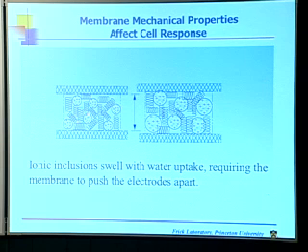Well, as the cell starts to run, it makes water. Some of that water ends up in the Nafion. Okay. Where does it have to end up? It has to end up in these pools. So these pools have to expand. Well, the only way the pools can expand is if the material expands or swells. It's pushing against those plates. Okay, so if it has to do that, it's got to do a lot of work to accommodate that water